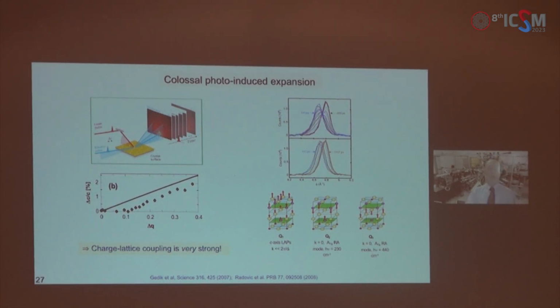We addressed this question through a pump-probe experiment in which a lanthanum cuprate film was excited by light pulses from a terahertz laser and probed by ultrafast electron diffraction. So the electric field of the light was perpendicular to the film surface, or on a couple of oxygen planes, the electric field is in plane. But as a response, we saw that the film blew up, expanded along the c-axis by as much as 2 or 3%. Now, this may look small, but for crystallographers, this is colossal because the lattice expansion from 0 Kelvin to melting point is something like 1%.